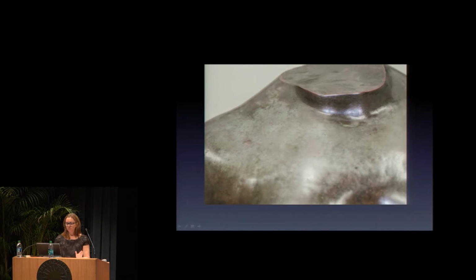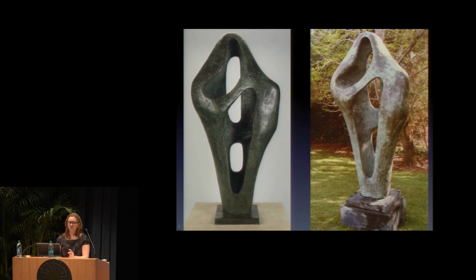So we were able to get down to a certain level, or Brianna was able to get down to a certain level, but we didn't really seem to remove all of the coating. I think there was some wax that was under the Incralac that was left over. And in order to get rid of that, we felt we'd have to be more aggressive, and didn't feel it was worth it at that time. So we just recoated and toned in a little bit to even out the surface. But it was still a very successful treatment, and I think it's a stable coating of Incralac, which is a whole other talk in itself on choosing which coating to use to recoat, but we are recoating with Incralac.